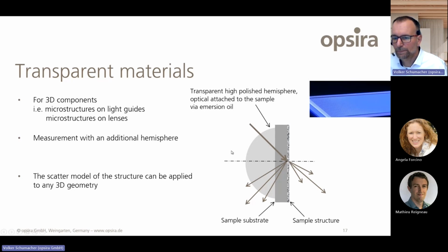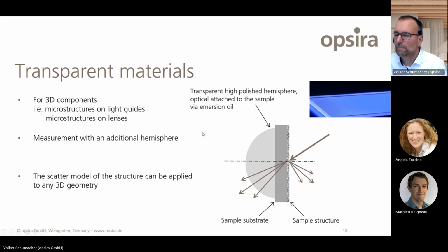And we want to know not only under a small angle, but also under a very high angle, under angles where total internal reflection can occur. To measure this effect, it's necessary to have this hemisphere. That gives us the possibility to shine under very flat angles onto that structure and measure in reflection and in transmission. We can also do it from the other side. Also here the light comes from air, and it goes via the microstructure, via the scatter structure. It goes to the substrate sample, and also we measure transmission and reflection. And again here the light comes from the substrate, and it will be measured in transmission and reflection.